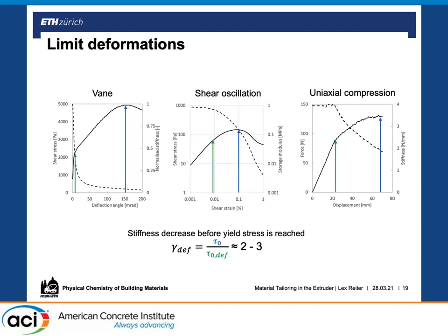About the interlayer, did you measure the interlayer bonding of the printed sample? Yeah, our process is constantly evolving. The process that we had about 2 years ago had basically no difference between the interlayer and the material itself. So we tested in different orientations. The paper is also now public, so I can give you that reference. However, that is not always true for everything that we do. In general, we have better experience with interlayer bonding when we have short times between layers and if we have a low yield stress at the time of placing.